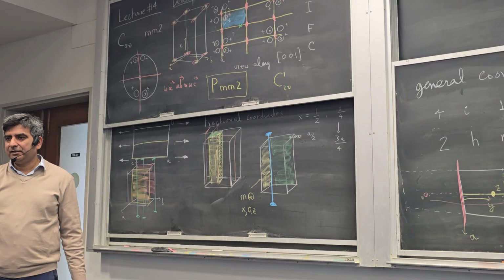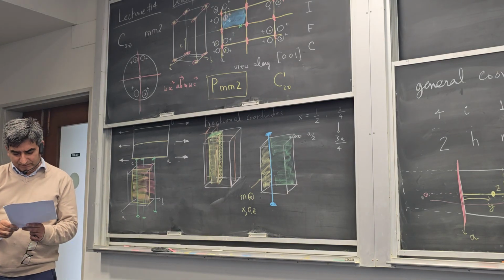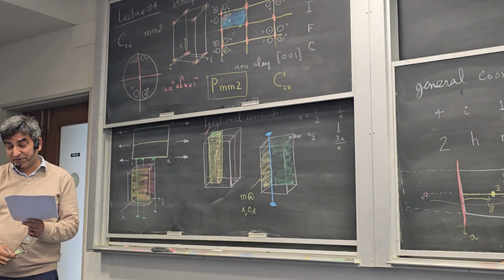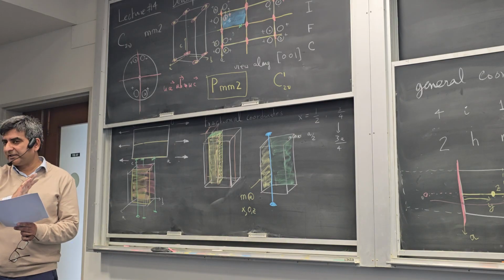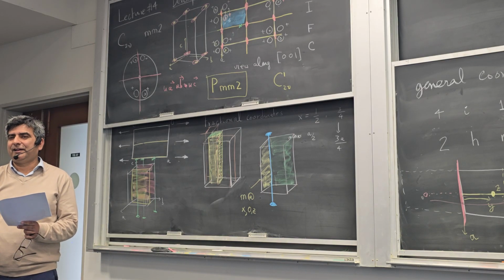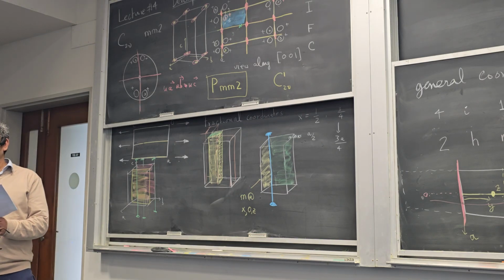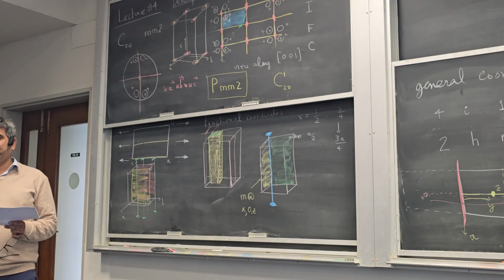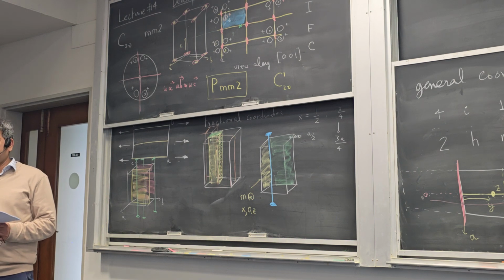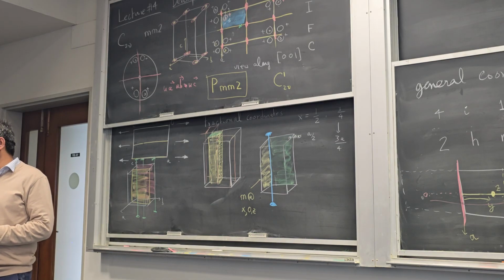So the symmetry is the lowest over here, right? Sorry, the symmetry is the highest over here, and the multiplicity is just 1. The entire line has an intersection of two mirror planes, one two-fold axis, so exceptional symmetry over here. The full symmetry of the space group is evident on this special position, on the 1A position, which means that if a point lies on this special position, it need not have a counterpart or a companion.